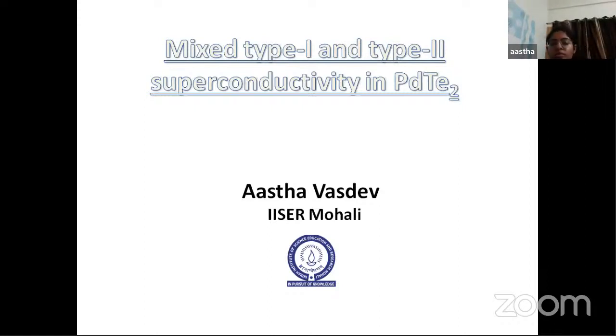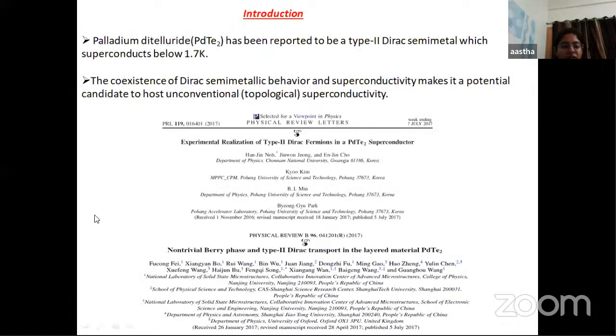So today I'll be talking about mixed type 1 and type 2 superconductivity in PdTe2. The superconductivity in PdTe2 has been reported for a long time, but it did not receive much attention because of its low critical temperature. However, after the discovery of the Dirac semimetallic phase in PdTe2, the superconducting phase also gained renewed attention, because the coexistence of a Dirac semimetallic phase and superconductivity in the same material might lead to topological superconductivity in the system. So here are the experimental evidences of the type 2 Dirac semimetallic phase in PdTe2.